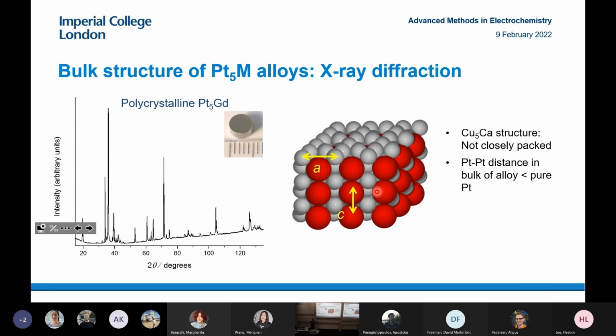If you de-alloy a platinum 3 structure, you probably form an intermediate layer of platinum 5 structure. And we tried to look at these platinum 5 structures with X-ray diffraction. And it was a nightmare to actually fit these XRD data because there are so many peaks. We found that the structure was a really, really complex structure. So it's not a closely packed structure. It's very different from the theoretical structures.